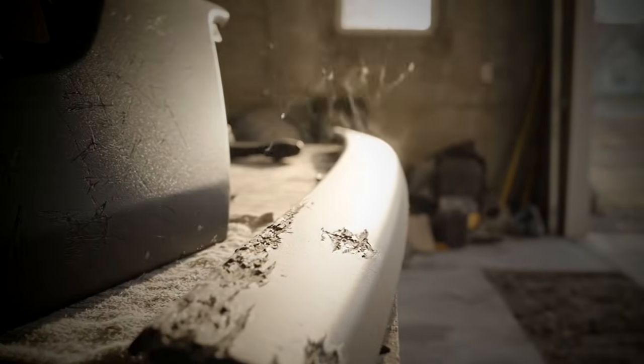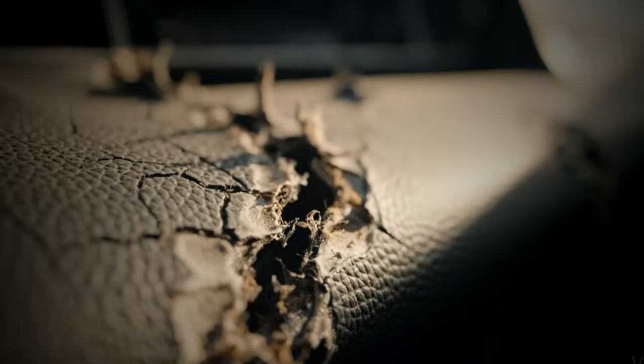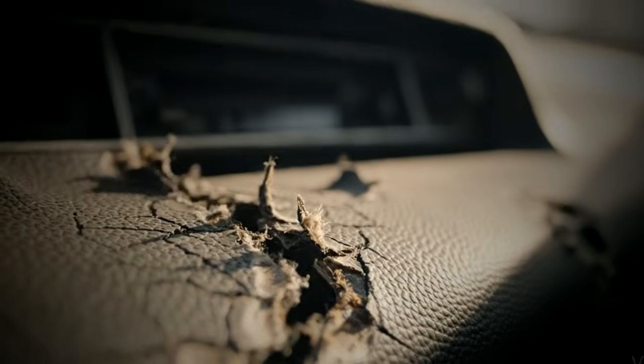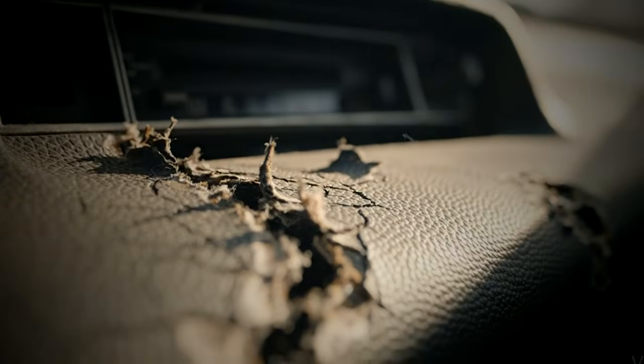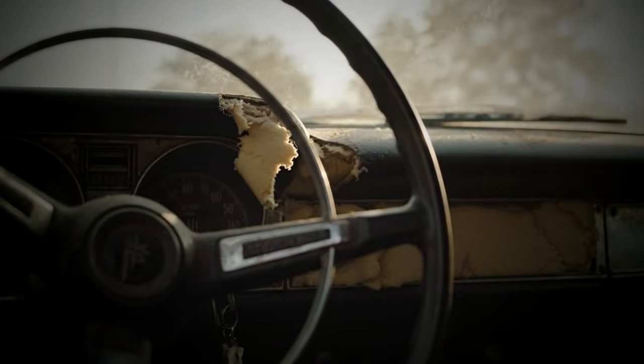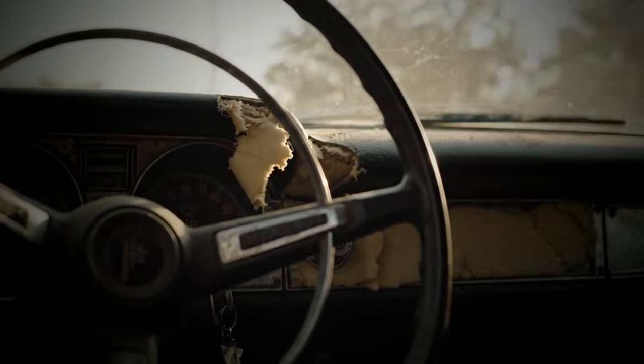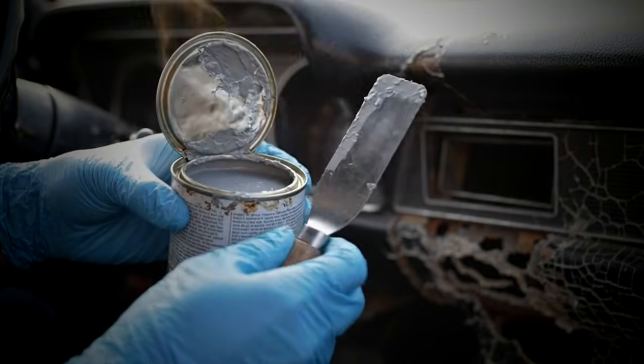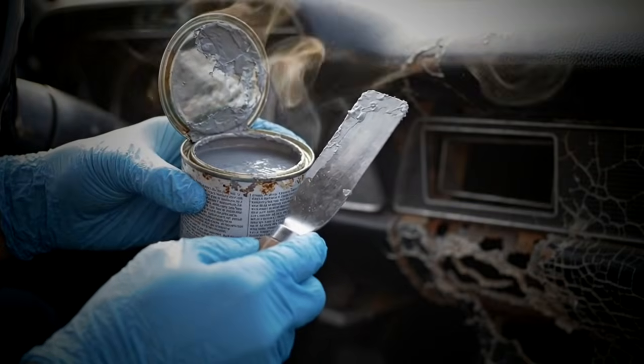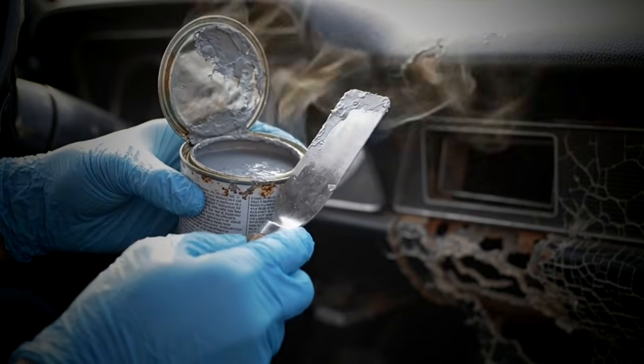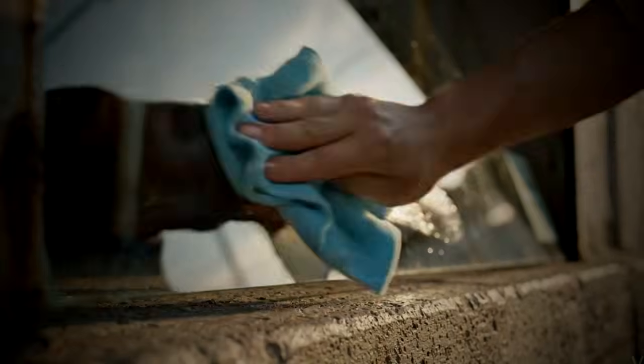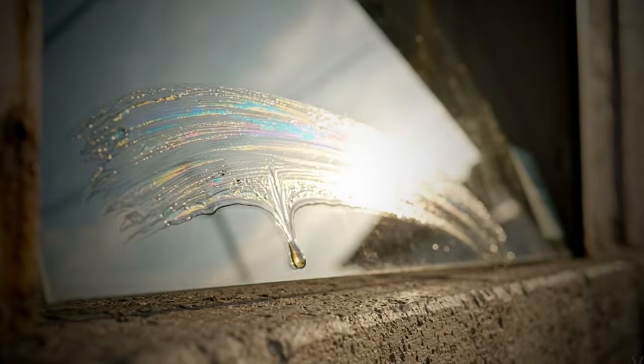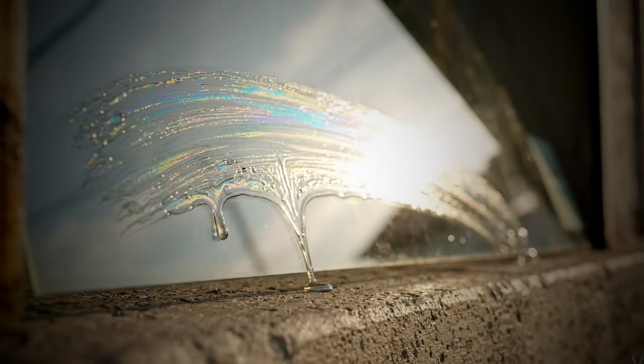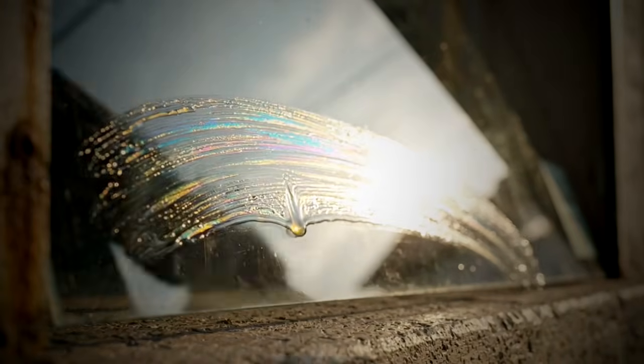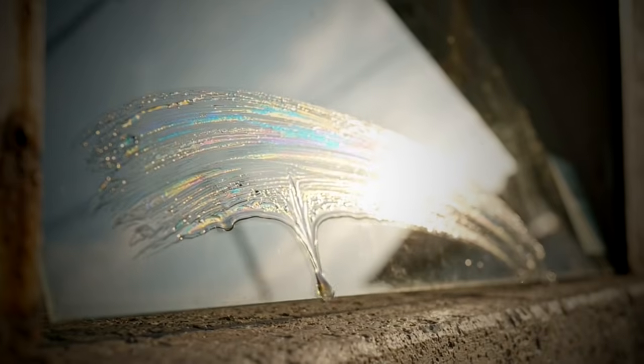Now the honest part. Baby oil, mineral oil, is excellent for hard plastic, ABS trim, polypropylene panels, and vinyl. It is not the right answer for every surface or every condition, and you should know the exceptions before you start. If your dashboard is already cracking and splitting, if the surface integrity is gone and plastic is peeling away in sections, oil will not reverse that damage. It will slow future cracking and restore some color, but it cannot fill a physical fracture. A surface that far gone needs a vinyl repair compound applied professionally before any conditioning makes sense.